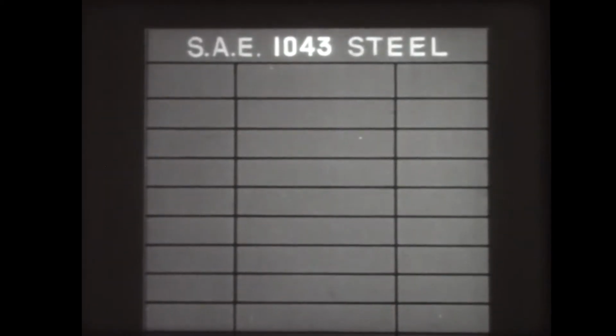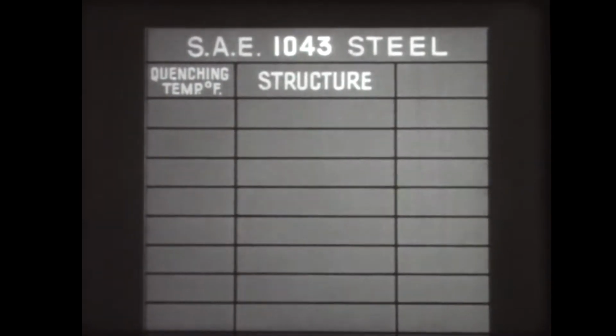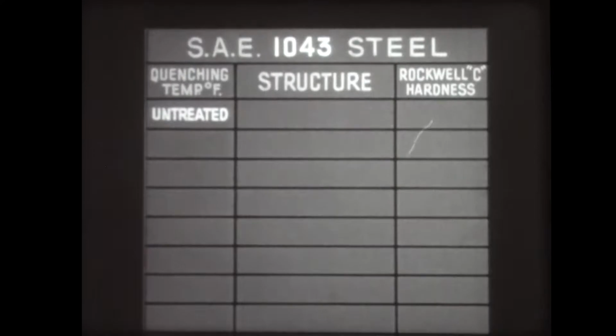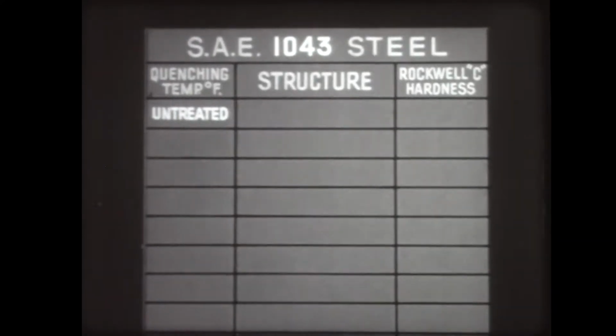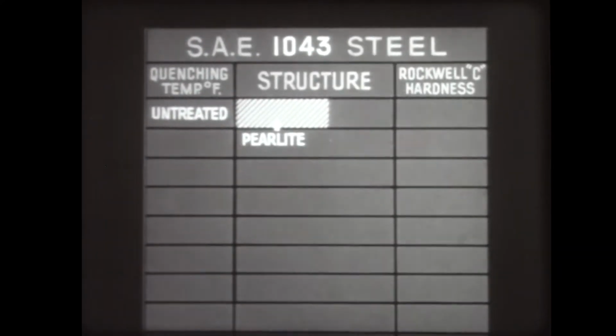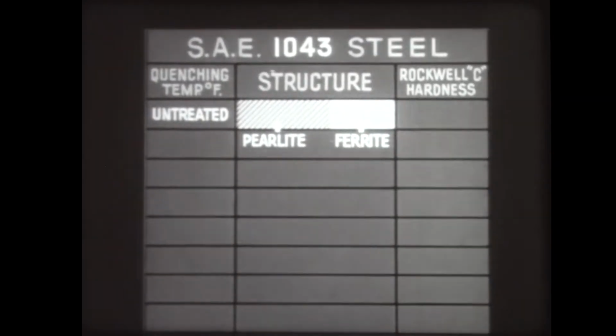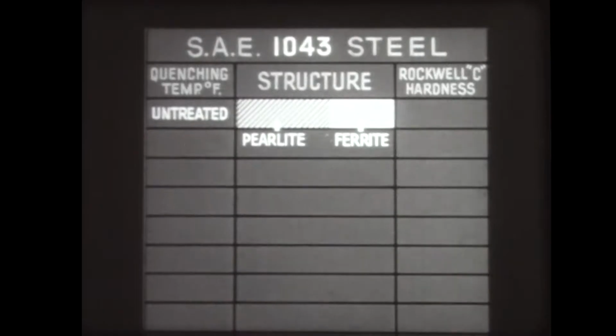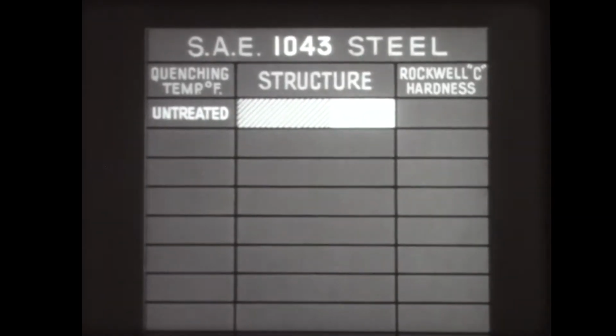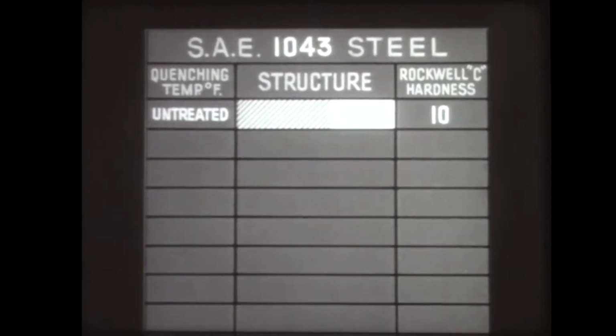On this table we shall record at progressive hardening stages the quenching temperature, the structural changes, and the Rockwell C hardness. We have seen that in its untreated condition, the structure of this steel consists of pearlite, graphically indicated here by light and dark layers, and ferrite, indicated by a white area. We also know that the steel's Rockwell C hardness is 10.